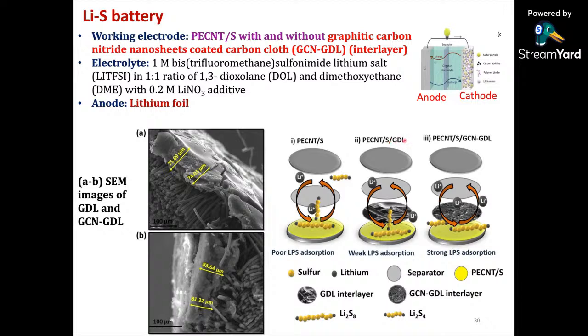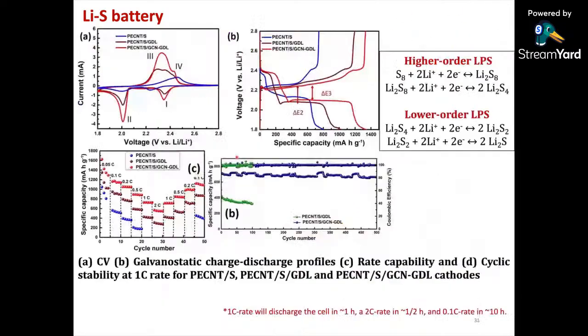This is PECNT/S, very close to that, a gas diffusion layer. This is just a carbon cloth, and then we have coated the graphitic carbon nitride. This is also a two-dimensional material. So this is the interlayer we use. Therefore, the cathode is PECNT/S, and we have the interlayer, graphitic carbon nitride coated on the GDL. You can see that. Then we have done the performance studies.